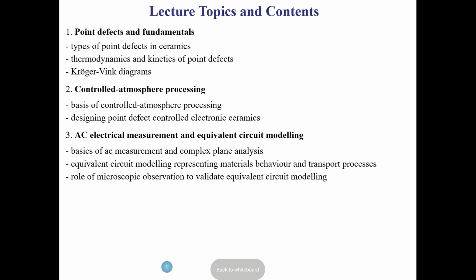Then I'll move on to a related topic: the so-called application of AC electrical measurement as opposed to DC measurement. For example, if I put two electrical contacts on a sample and measure electrical conductivity, I can apply voltage, measure current, apply Ohm's law, get a resistance value for the entire sample, and then by looking at the electrical contact area and the distance to the electrode, I can convert it to conductivity, the inverse of resistivity.